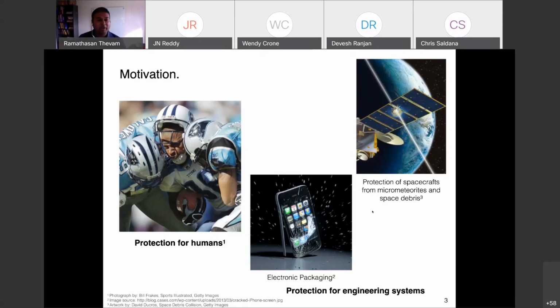Or else it could be like the spacecraft that are seeing increasing threat from space debris and micrometeorites. When you look at these events, one thing you can immediately see is the impact velocities vary drastically from 1 to 10 meters per second in these small impacts versus several kilometers per second impacts in space, right? So they correspond to very different strain rates in different types of materials. One thing that is common in all these conditions is that materials are pushed to the extreme. So we need to design materials that can perform in these extreme conditions.